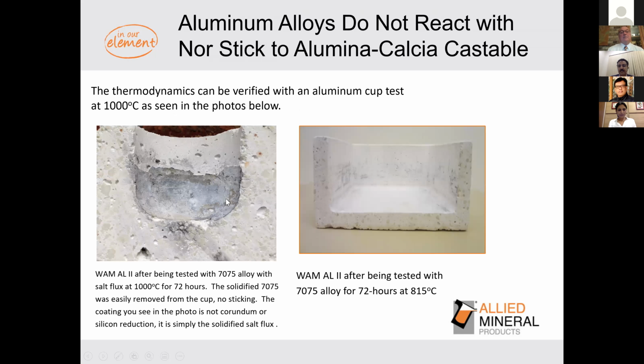On the left here, again, we ran the aluminum salt flux test. And what you're seeing here is not aluminum. The aluminum slug, the molten aluminum, when it solidified in this cup, was able to be withdrawn from the cup just with their fingers, pulling it out. No sticking at all. This is only the solidified salt flux that's left in the cup. And as you can see in the interface, zero reaction.